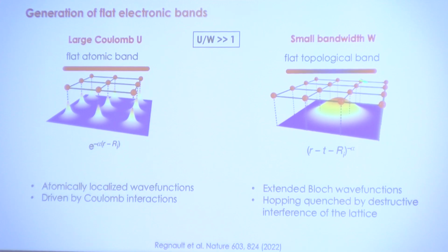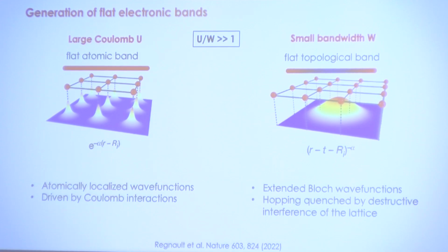On the other limit, we have also seen a lot of examples in Stephen's talk and also later talks. You can quench the hopping using special lattices, and you can see that the Bloch wave functions now no longer sit on the atomic sites, but somewhere in the middle, and they're actually kind of large. There is overlap, but the hopping is quenched by the destructive interference of the electronic wave functions. So these are fundamentally distinct, and from a spectroscopy perspective, they also look different.